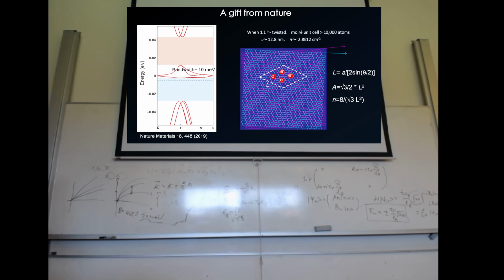The moiré unit cell is in an experimentally favorable size. When you have two graphene layers twisted, for example at 1.1 degrees, I will go to that slide later, you have a moiré length of only 12.8 nanometers. Correspondingly, a full filling of this moiré unit cell with four-fold degeneracy, four electrons, gives a carrier density of only 2.8 times 10 to the 12th per centimeter squared. That means using conventional CMOS technique through any kind of dielectric, you can easily obtain that. And the limit we showed you yesterday, the maximum carrier density through a gated dielectric, is about 1 times 10 to the 13th, right?